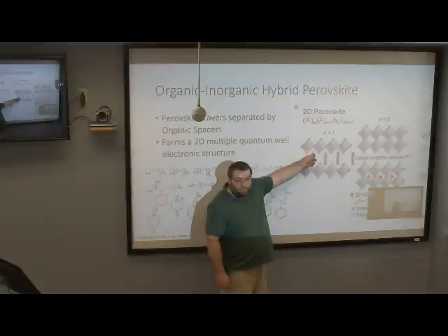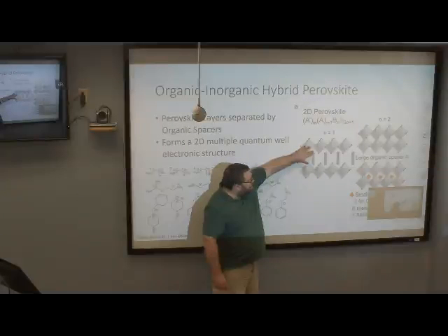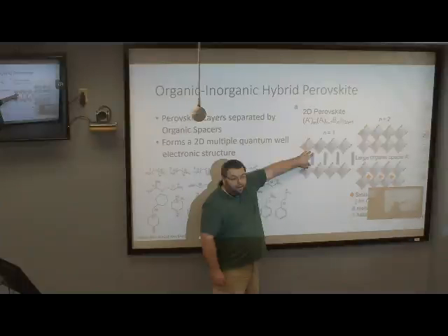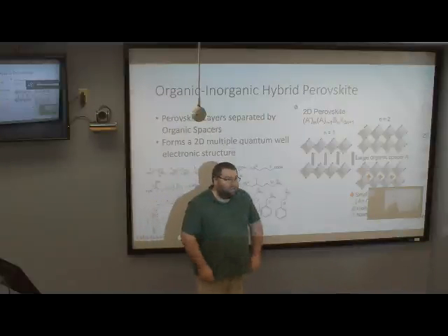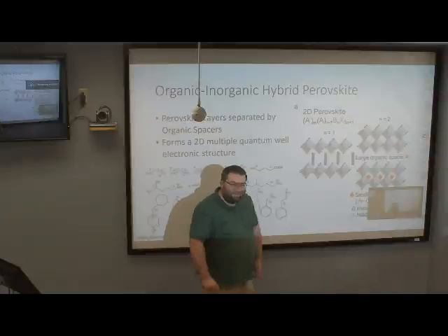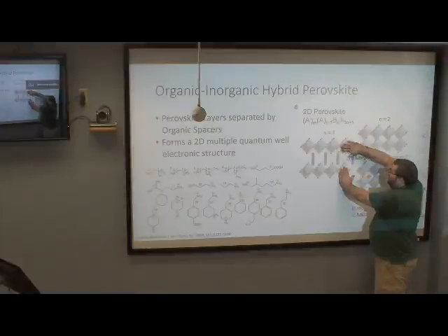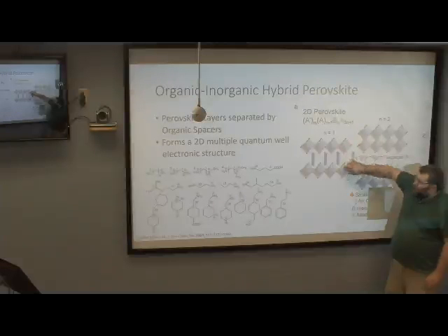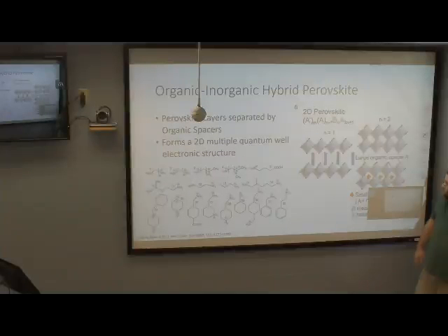So you need another second one down here. In the diammonium case, you end up with an ammonium on both sides, so it can directly bond to both perovskite layers. Excellent. Which causes, in the Ruddlesden-Popper instance, your two perovskite layers to be offset. These ones are actually drawn as Dion-Jacobson, where they're in line. Okay. I have a quick question.